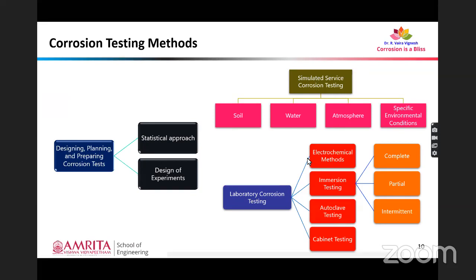But when we have to test the corrosion rate of materials for an extended period of time, then immersion testing will not work out to a great extent. So for those cases, we have to move towards electrochemical methods of testing or evaluating the corrosion phenomenon that is taking place in the material. We'll first see the basics of electrochemical corrosion test with respect to potentiodynamic polarization in detail, then we'll go ahead with the results of our study.